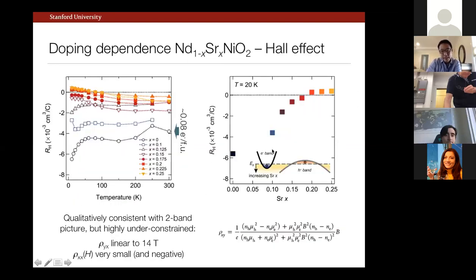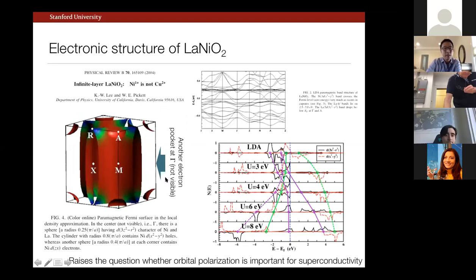And again, this cartoon is pretty consistent with, and was certainly motivated by, the results of band structure calculations. So again, going back to this paper by Lee and Pickett for lanthanum, neodymium is basically the same, by the way, nickelate, you have these large hole-like pockets from the x² - y² states.